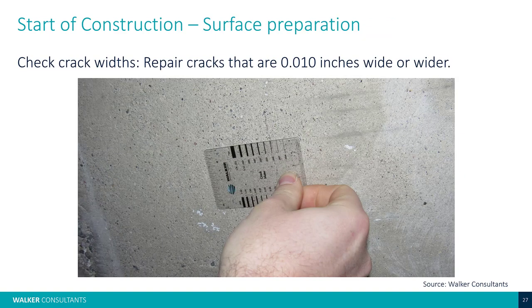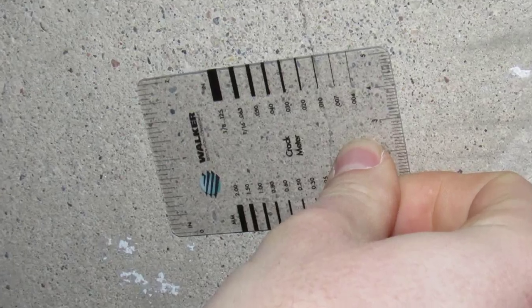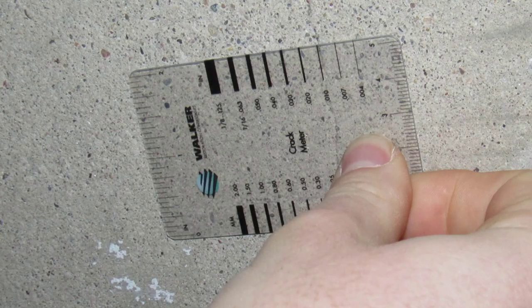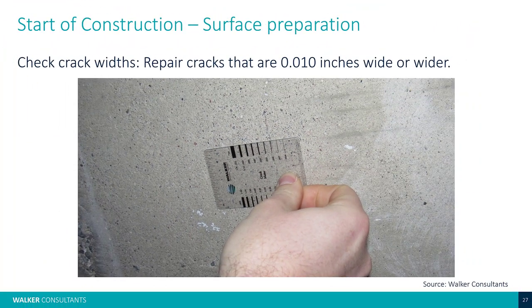So checking crack widths. Specifically in ACI, we want to repair cracks that are 0.01 inches wide or wider. So here I am in the photo, actually checking a crack that I found in a beam. Sometimes these cracks are very hard to find. So you're going to look for everything that you can out there, and then you want to take a crack comparator and actually look at how wide those cracks are and repair them. So the automatic is anything 0.01 wide or wider, you're repairing.